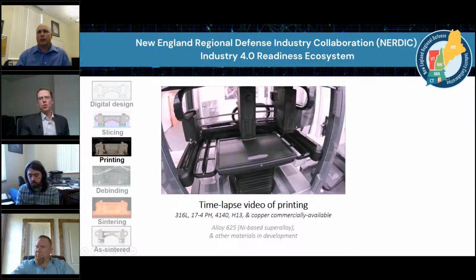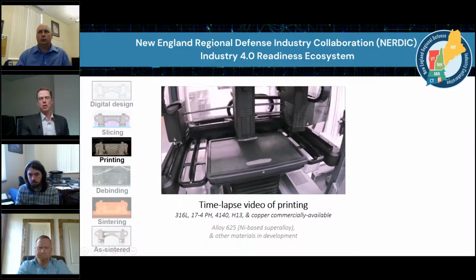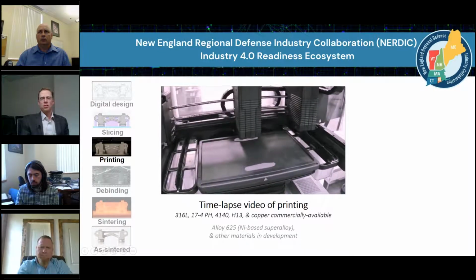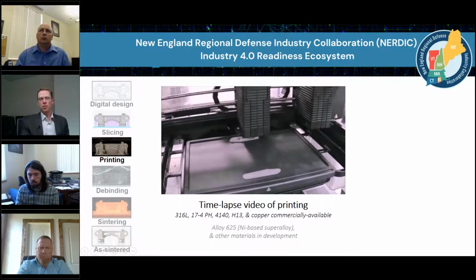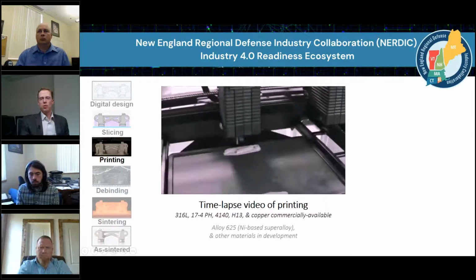If we look at printing, you'll recognize this if you have a residential scale polymer machine. It's a very similar process. You start off with a rod of material from the manufacturer, and it goes through almost what you'd imagine as a hot glue gun. It's heated and forced through an extrusion nozzle, in this case a 400 micron nozzle, and through the G-code it prints the part. Currently, these materials include 316L, 17-4 PH, 4140, H13, and copper, all commercially available. There's a nickel-based superalloy being developed, as well as other materials in development.